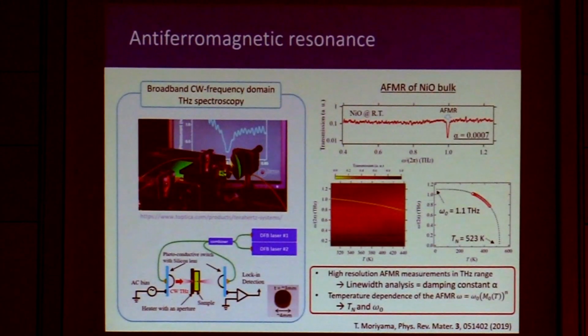Okay. So the next topic is antiferromagnetic resonance. Recently, we introduced this broadband CW frequency domain terahertz spectroscopy in our lab. So now we can characterize the transmission absorption. We can do the transmission absorption measurement for the bulk antiferromagnetic material, not the thin film, unfortunately. We are working on that. But the typical nickel oxide spectrum is like this at room temperature. As you can see, at 1 terahertz, we have a very sharp absorption.